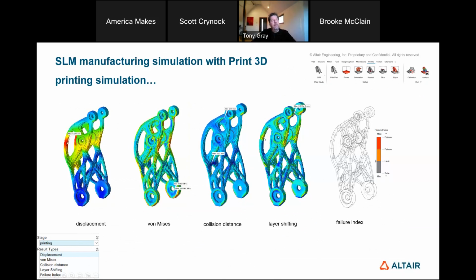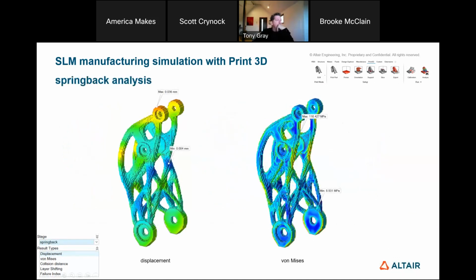Layer shifting, so you can get kind of marks appearing in your print, and then we also calculate a failure index. And then there's also a spring back phase. So you can see how much your part springs back and any residual stresses after the printing. This spring back is very important to get your final net shape. You want to know that it's close. So again, you would probably change your design that you printed to add material that could then be machined out, kind of in the key connection points.